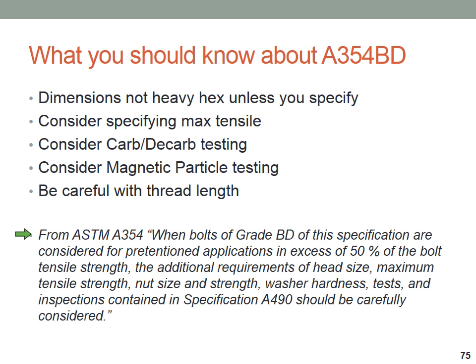You should consider specifying a max tensile, because there's no max tensile strength in 354 like there is in 490. You should consider specifying carbon decarb testing, which is not a requirement of 354, but it is of A490. You should consider specifying magnetic particle testing, which is a requirement of A490 but not A354. And again, be very careful with the thread length. You will, by default, get longer threads on an A354 than you will on an A490 unless you specify the thread length. So keep that in consideration as you design connections that might be using 354s that are shear or bearing type.